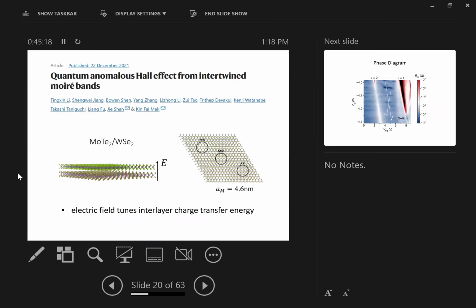Okay, so what's really interesting is an experiment from last year on MoTe2/WSe2 again by the Cornell group. And here it was found that the system shows a very interesting phase diagram, not just the Moiré insulating state, but many other states. And the magic here is that you can apply an electric field between the 2 layers. I'm going to show a phase diagram as a function of filling, doping, as a function of electric field.